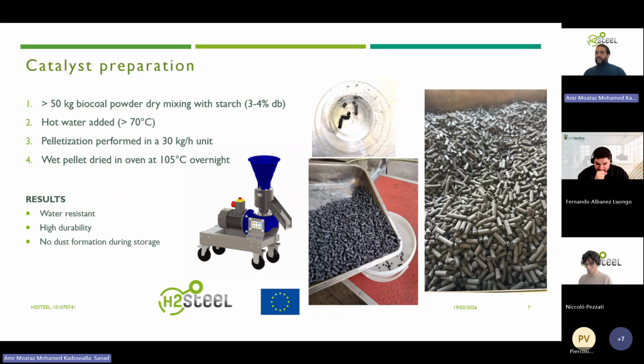As for the catalyst preparation, the catalyst is prepared in-house, as was mentioned earlier, and it starts from the production all the way to the preparation for test. The main preparation step after the production is pelletization, which requires at least 50 kilograms of biocoal in powder form that is dry mixed with 3 to 4% of starch. Hot water is then added and pellets are formed in a 30 kilogram per hour unit that is shown in this figure. The pellets produced from this pelletization process are presented in the pictures on the right-hand side.